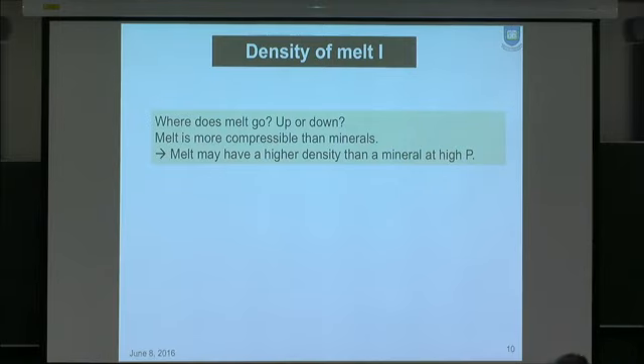The bottom line is there are two things which control this density business. First point is melt is in general much more compressible than minerals. In terms of bulk modulus, various minerals at ambient conditions are on the order of 100 GPa. But bulk moduli of various melts at low pressure conditions are 20 GPa or 30, amazingly low. We developed theory to explain this, and this causes the very rapid compression of melt, so that the melt might become denser than solid.